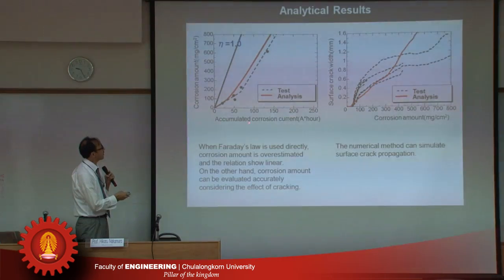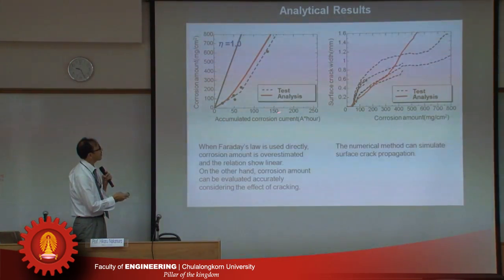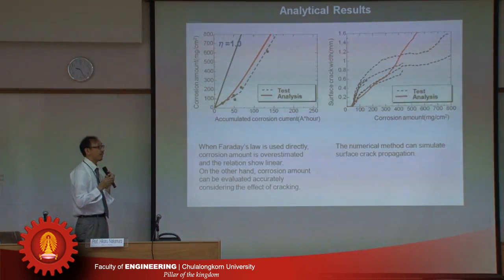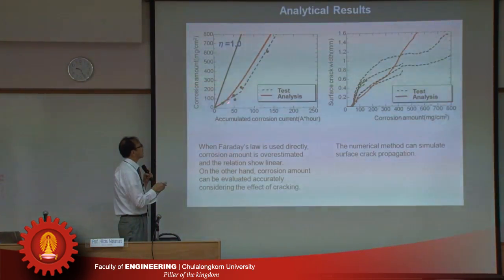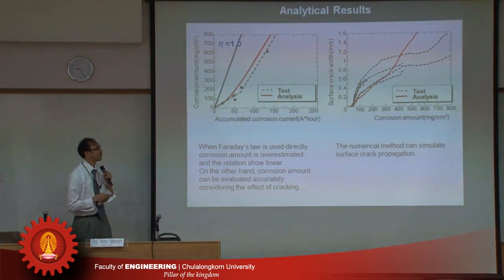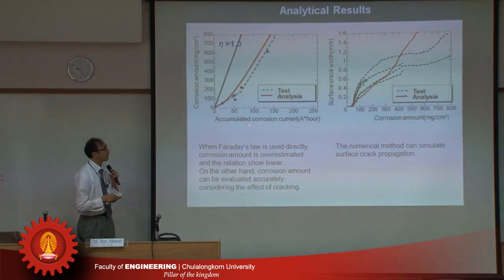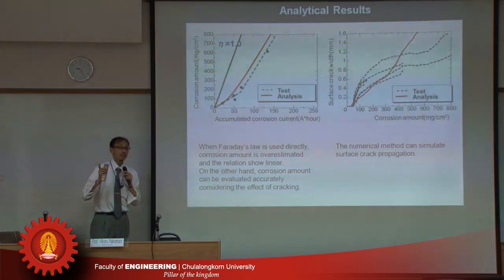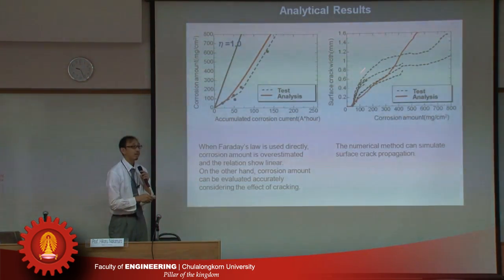This relationship is between the accumulated corrosion current and corrosion amount. This is a test result. When we use Faraday's law directly, it overestimates. But when we consider the effect of the concrete and the effect of the crack, we can simulate the test result reasonably. This simulation is very important because the accumulated corrosion current is directly related to time. It's just time. So we can simulate the effect of time.